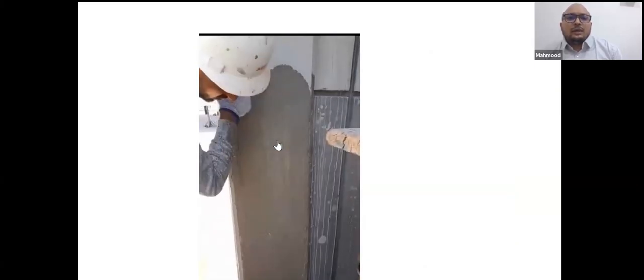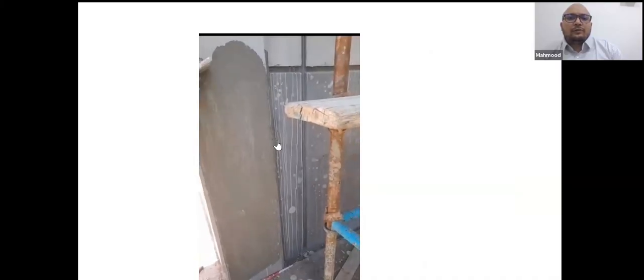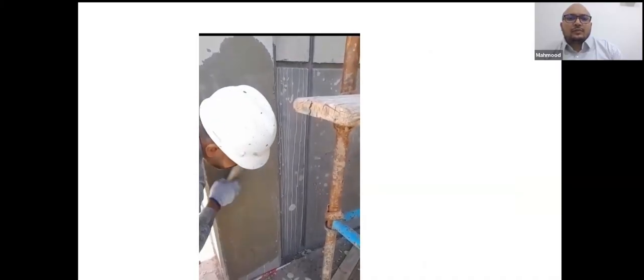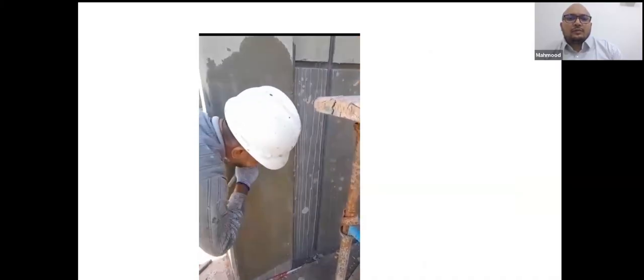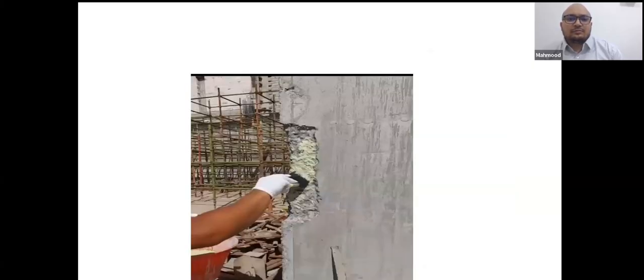They are applying a polymer modified cementitious surface material to fill the blowhole and pinholes. Previously, we saw the repair for the floor. Now, this is the repair for the vertical one.